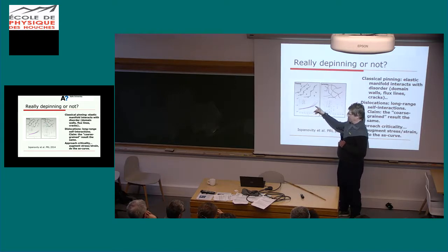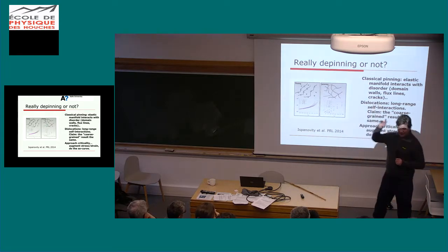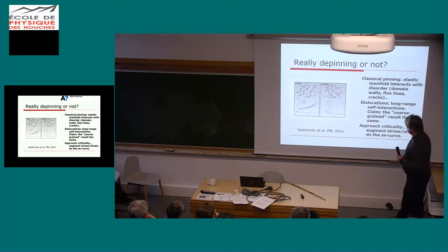You see that they increase in size very slowly, and in the proximity of a critical point, you start to see the divergence at values of external stress that depend on the system size, so you get the corrections to the phase transition critical value.